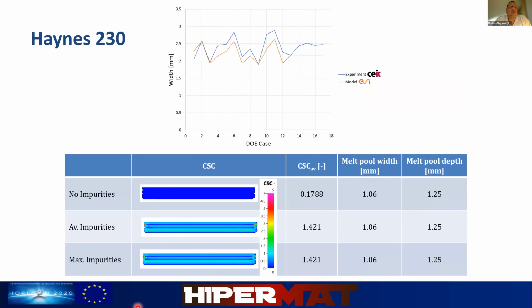We have done quite a series of simulations for Haynes 230. Here data was measured at CEIT for different DOE cases. And as you see, we capture the trends very well. There are small differences. It could be experimental noise, numerical inaccuracies, maybe discrepancies in properties. But in general, it's a very reliable prediction with a very good capture of